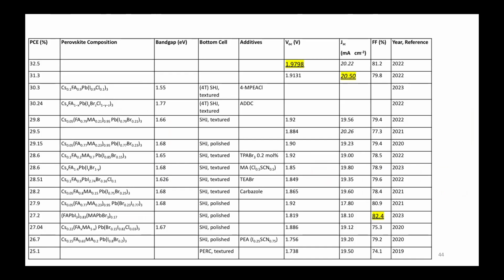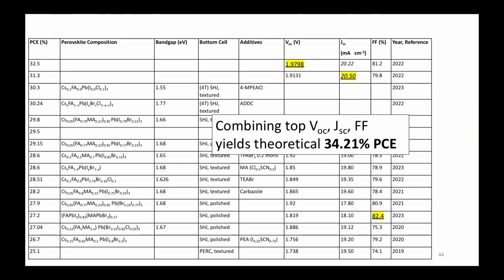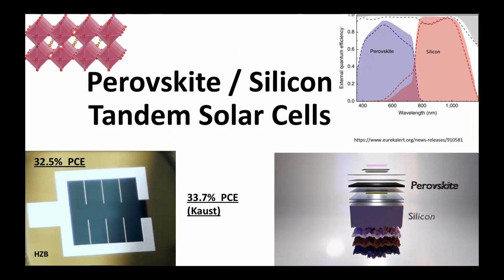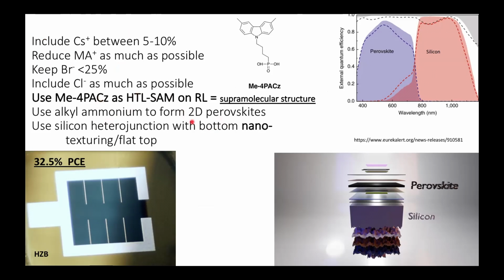And one more thing. If you take the best values from what has been reported, the best voltage, the best current, and the best fill factor, you can anticipate 34.2%. So that should be attainable. It can be done. Perovskite silicon tandem cells. And the message is, we're using supramolecular chemistry. We're using a self-assembled monolayer as the hole transport material on top of the recombination layer.